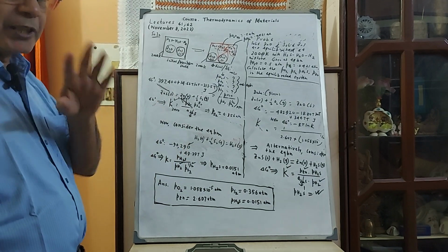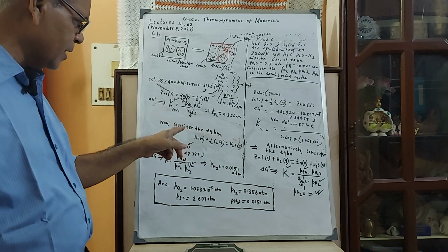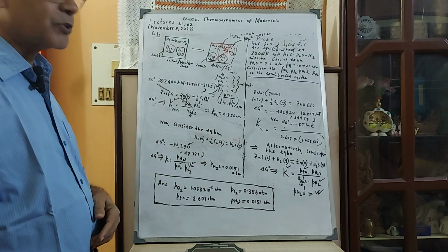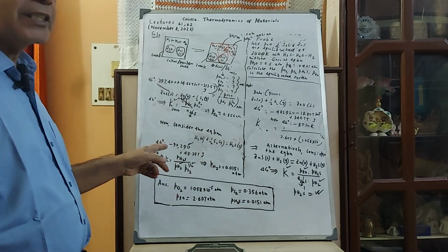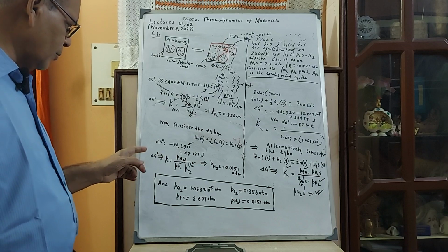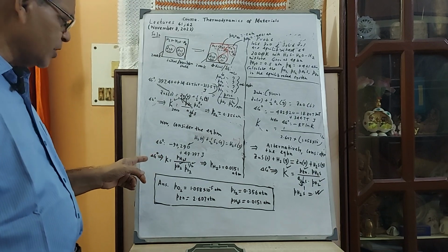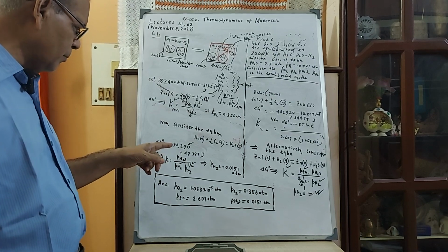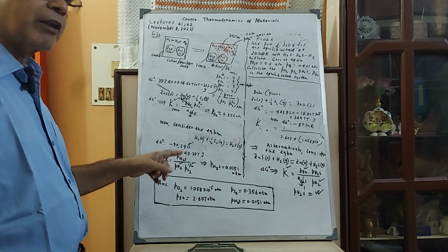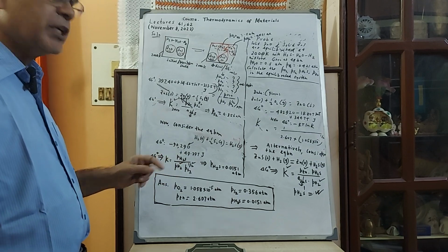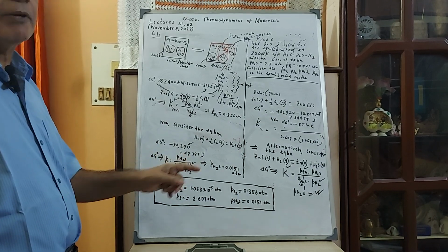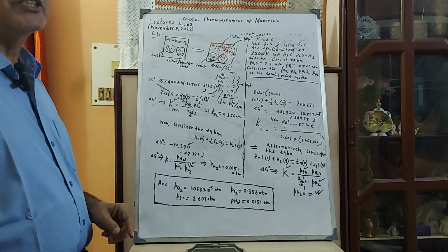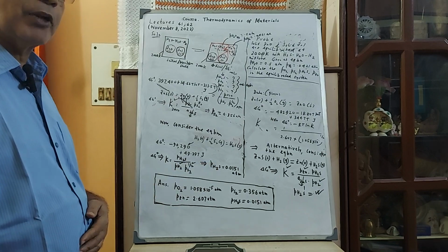Consider this simple equilibrium: hydrogen plus sulfur half, H2 goes to H2S, and delta G0 is given here. You get the equilibrium constant from delta G0 = -RT ln K. Write the expression at equilibrium, pH2S by pH2 power half. Since pH2 is already known, there is no difficulty in finding pH2S, and the value is 0.0151 atmosphere. So all four are determined.